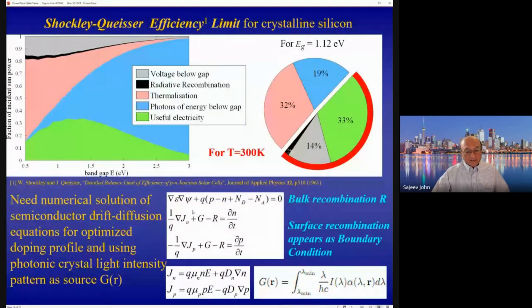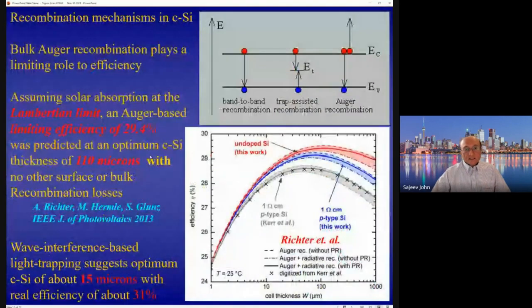So it's a very complicated exercise, but first let me talk about some of the recombination mechanisms that define what the real limiting efficiency is. So in the bulk of silicon, there are three possible recombination mechanisms that one needs to consider. One is that the electron that has been excited to the conduction band edge recombines with the hole at the valence band to re-emit light. That is very unlikely to happen because silicon is an indirect bandgap semiconductor.